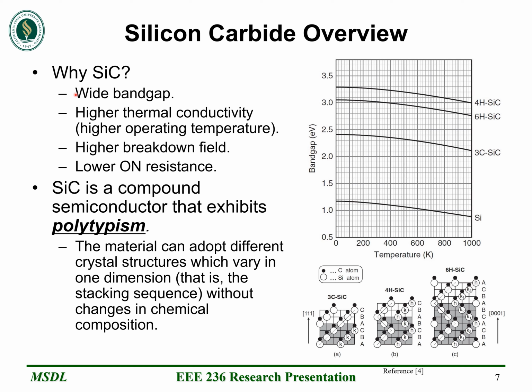So let's look at the band gap for silicon carbide as an example. On the right, we plot the band gap energy in electron volts as a function of temperature for silicon and 3 different polytypes of silicon carbide. We'll touch on what polytypes are in just a little bit. So if we look at 300K, regular silicon has a band gap energy of about 1.1. But if we go all the way up to 4H silicon carbide, you can see that at the same temperature, it has about 3 times the band gap energy of regular silicon. This is evidence of why we would want to use silicon carbide for high power applications.